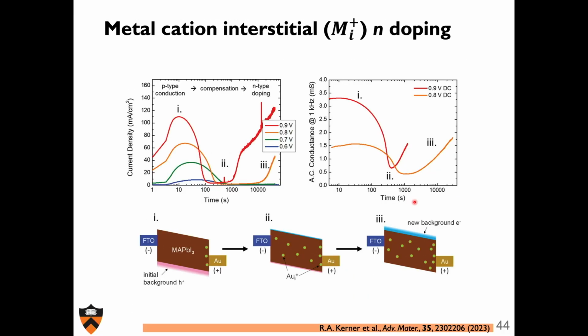And so we conducted these very, very simple tests. This is looking at current as a function of time for different step-ups in the voltage. And what we saw was that initially we had reasonable conduction, and we thought this was initially p-type conduction, the Fermi level that we typically measure of methylammonium lead iodide on FTO. The Fermi level sits slightly in the p-type range, and so it's consistent with some kind of p-type hole-dominated conduction initially. And then as a function of time, you can see that eventually the conduction goes down.